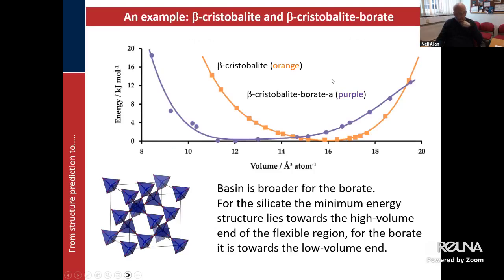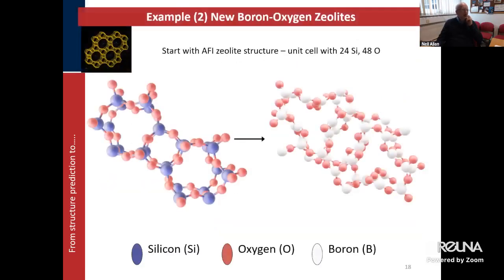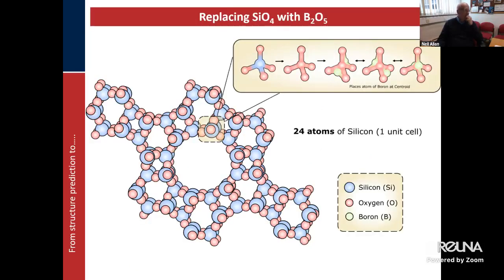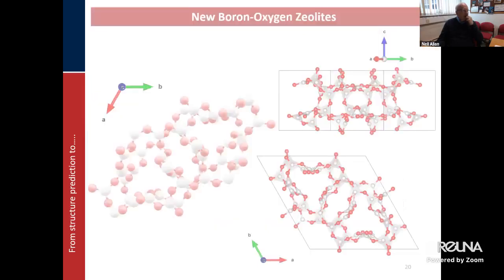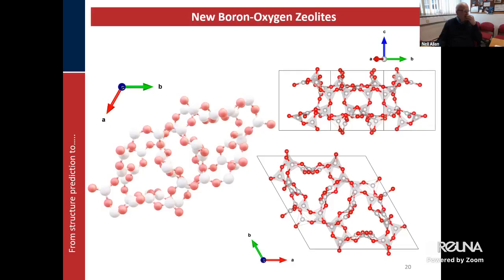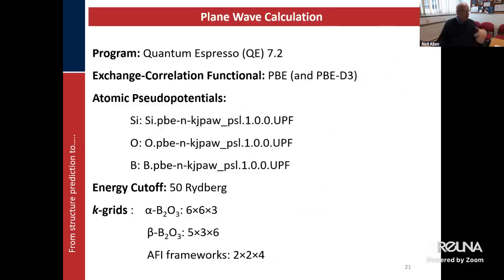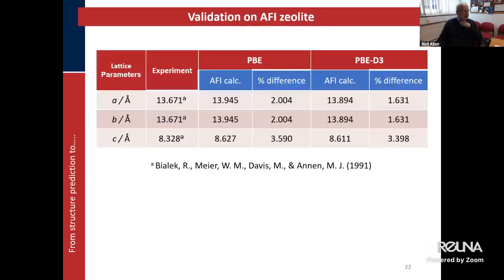So very recently, we've started looking at zeolites with a former PhD student of mine, now based in Thailand. And so we can replace all the SiO4s with B2O5s. Here's some pictures of the result, having generated the new ones. Again, this was actually some PBE calculations. I'm going to come on to dispersion briefly later. We tested the methods on the original silicate zeolite, reproducing lattice parameters and structures well.